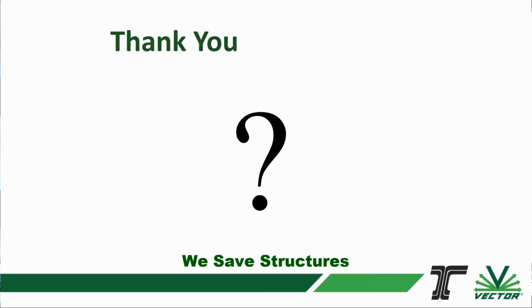First one I have is some questions that came in pre-webinar. What factors affect the quality of the application, adhesion, and long-term performance of the coating? You mentioned specifically temperature and humidity. Is there anything else, and what time of year did you do these? Was it in the summertime? Well, I would say moisture is probably the biggest thing you have to be careful about, because if you have any free moisture on the concrete surface or in that surface layer of the concrete, because you're spraying hot material onto the surface, you're going to create steam, and that's going to create a poor bond. So making sure that you're well below the dew point is key, and making sure that the concrete surface, like if you're doing concrete repairs, that you've left them long enough that they've dried out sufficiently, etc., those kind of things.